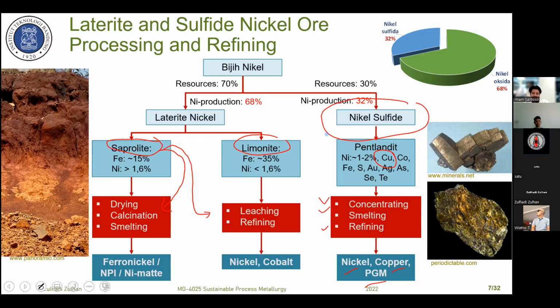For limonite nickel ore, the common technology is actually acid leaching, which can be divided into two types: atmospheric leaching and high pressure acid leach. And from the limonite, we can recover nickel in the form of mixed hydroxide precipitate, or after that we can refine it further to nickel sulfate or even to metallic nickel. Similar also with the cobalt. The product is what we call class 1 nickel. For sure, class 1 nickel is more expensive compared to class 2 nickel.